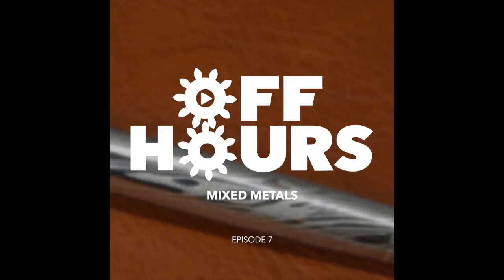And for the etching side of things, do you have a go-to etch that you like to use, or do you just use acids you've got kicking around? You can't just use whatever you have kicking around. For instance, I have nitric acid in the shop that I use for various things, and that doesn't touch stainless steel at all. So in this case, you use muriatic acid, and that attacks the 316 stainless and etches it. Depending on how warm the acid is and how long you leave it in there, it will go from being just a very, very delicate etch, which really just brings out the texture and shows you the difference between the 304 and the 316.